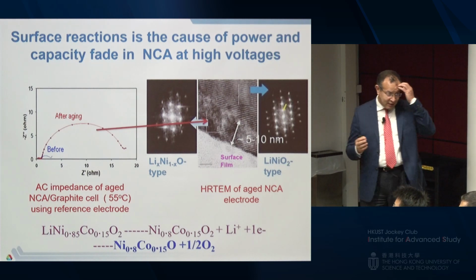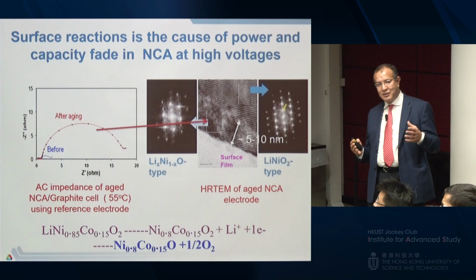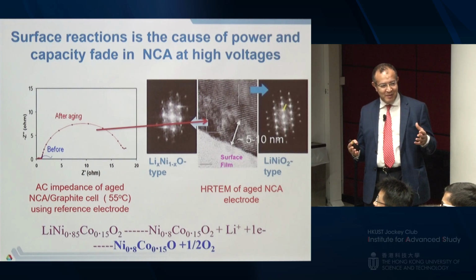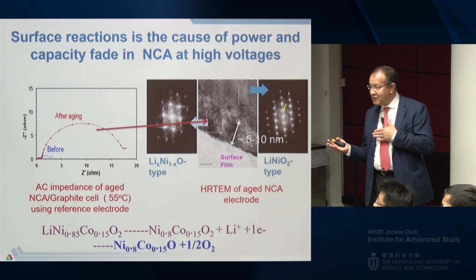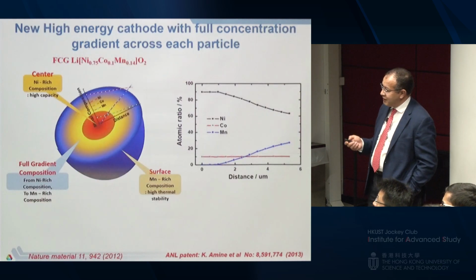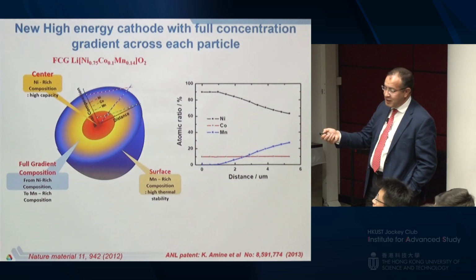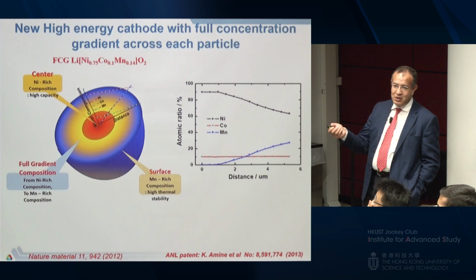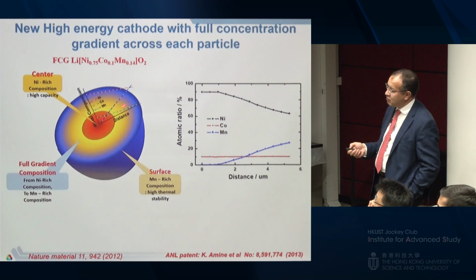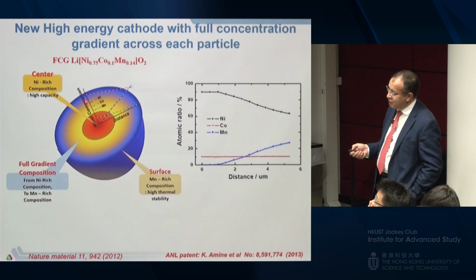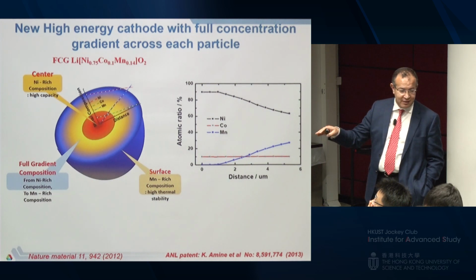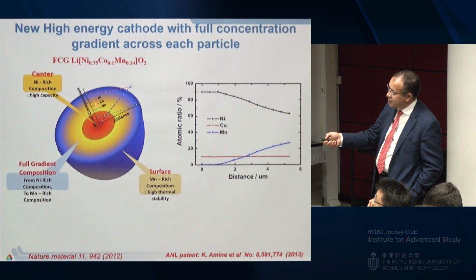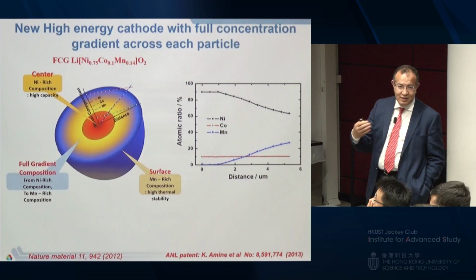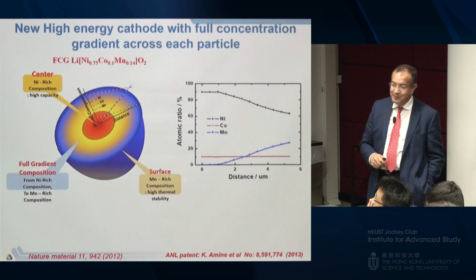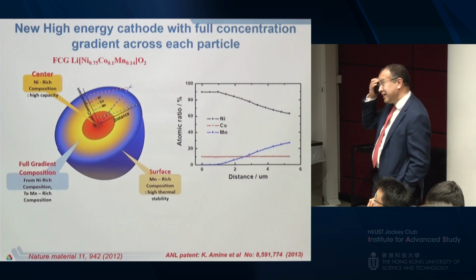Now, what we learn from all this is that when you use a very high nickel concentration in a cathode, you get very high capacity, but then you have a problem with cycle life. To address this, we developed this material that has now been licensed and is being scaled up for application in electric vehicles. We call it a full gradient cathode material. This is the first time you have a material that has changing composition across the particle. You start nickel rich to give you the energy and slowly reduce it and increase the manganese to get more stability at the surface, which prevents the reactivity with the electrolyte I showed you. So a very clever approach by engineering the particle.